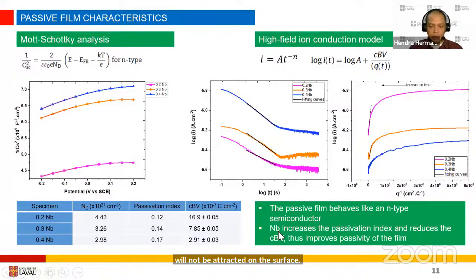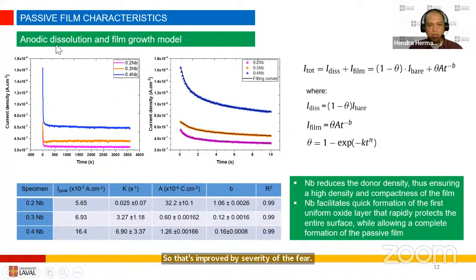CBV is a parameter related to ion migration in the passive film. So it does improve the passivity of the film. Okay, and then by using the anodic dissolution and film growth model, we arrive at this conclusion that niobium reduces the donor density, thus ensuring a high density and compactness of the film.